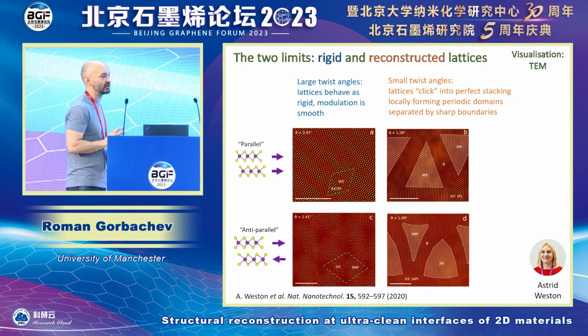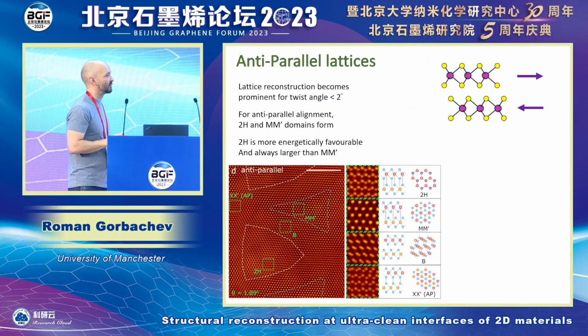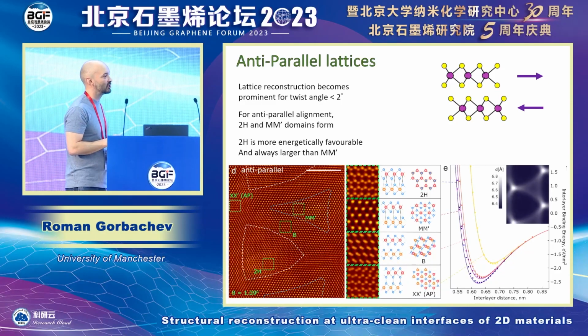But it is only, say, 10 or 20 nanometer island of perfect bilayer. And in between, you have the boundaries. So the reason it is forming is because 2D materials really like to click into each other in terms of energy favorability. And if you plot adhesion energy as a function of different stacking orders, you can see that really the lowest energy you have is for 2H stacking. And this is the stacking 2D materials usually grow in when you grow in the bulk, because it's the most favorable. But there are others that you produce that don't grow naturally. For example, this domain here.